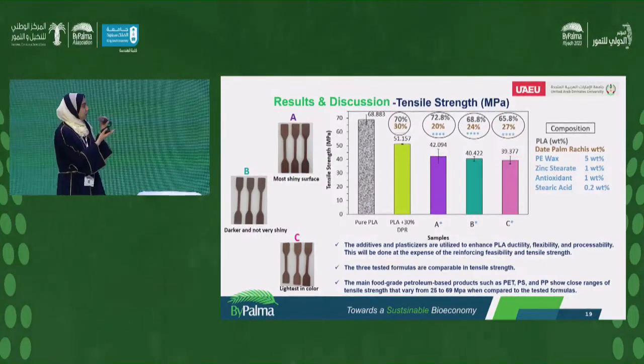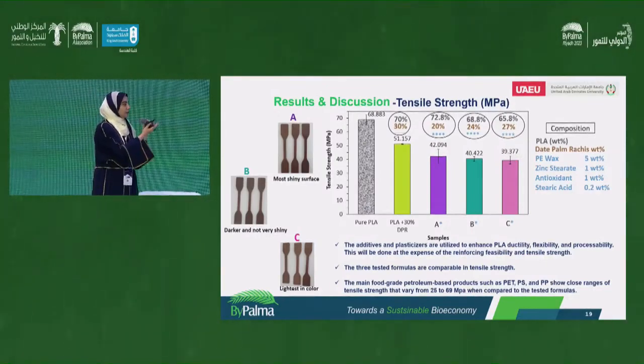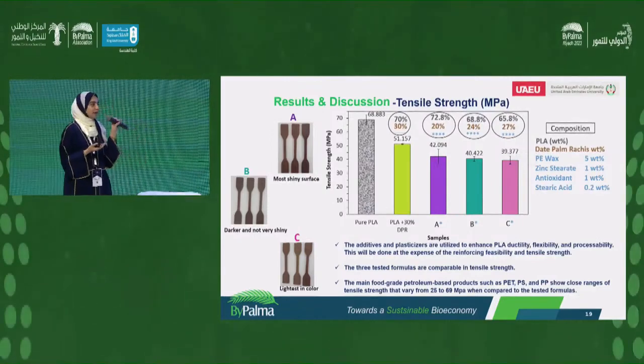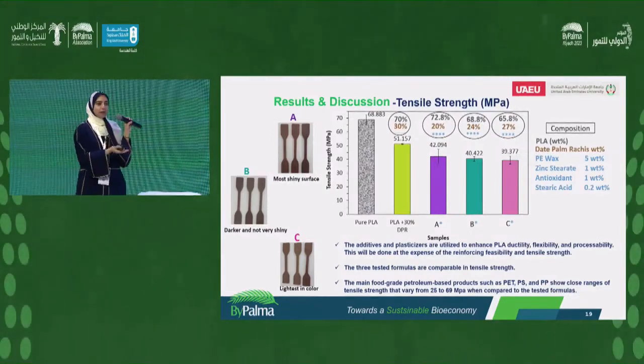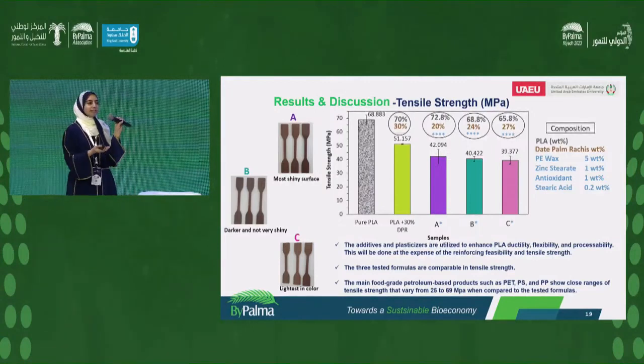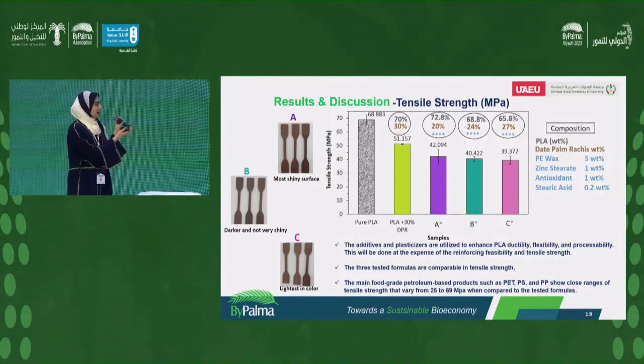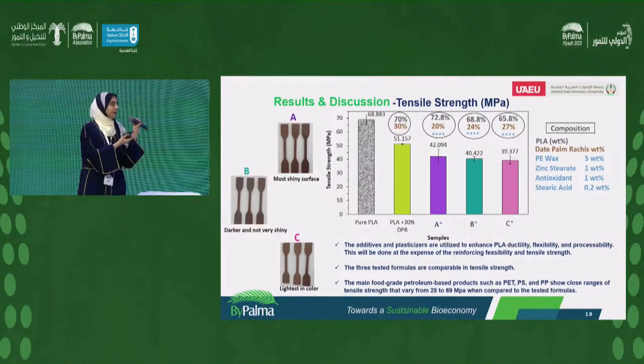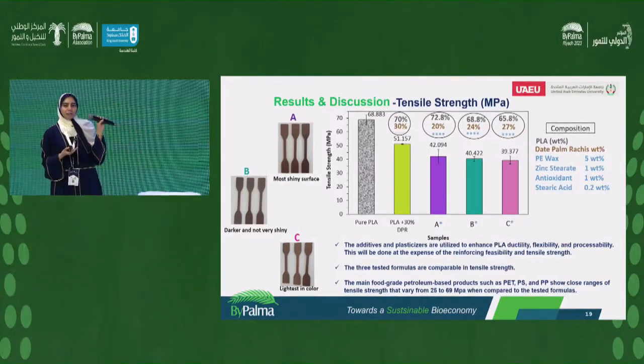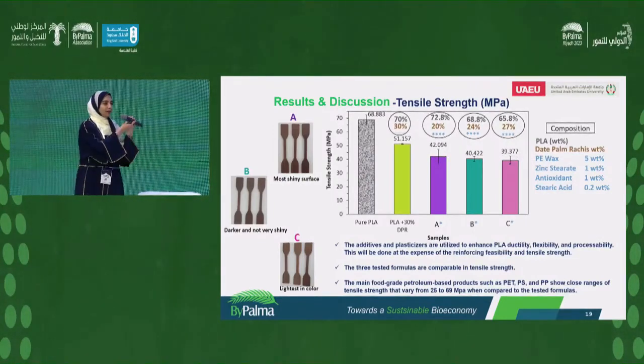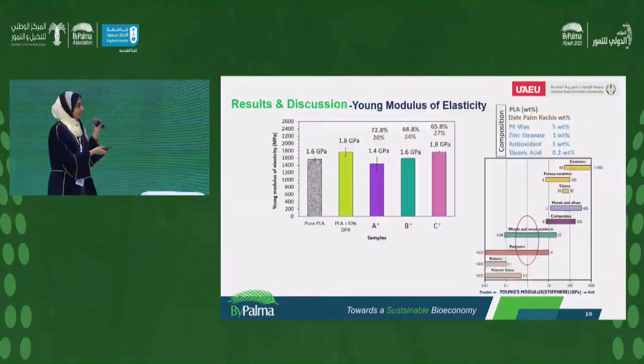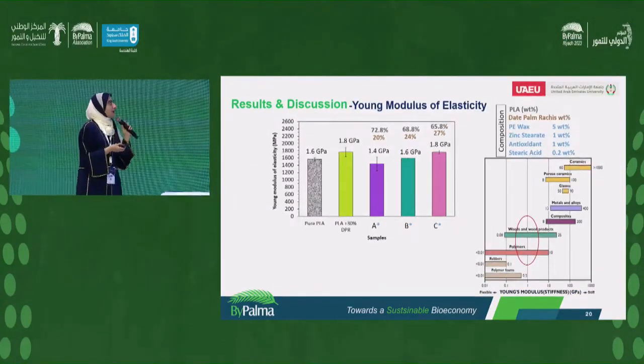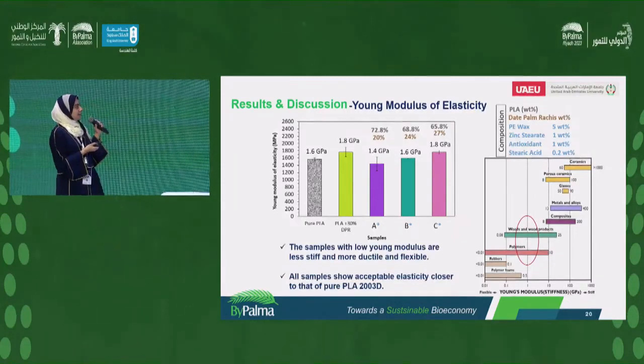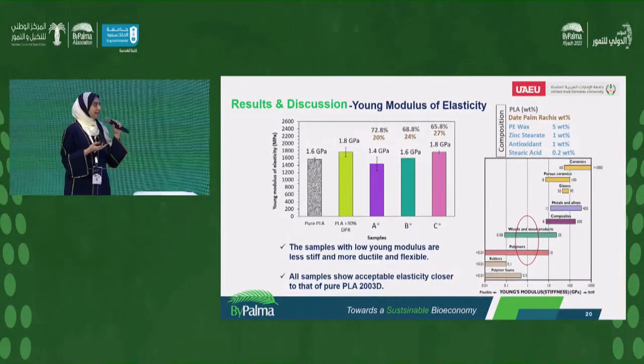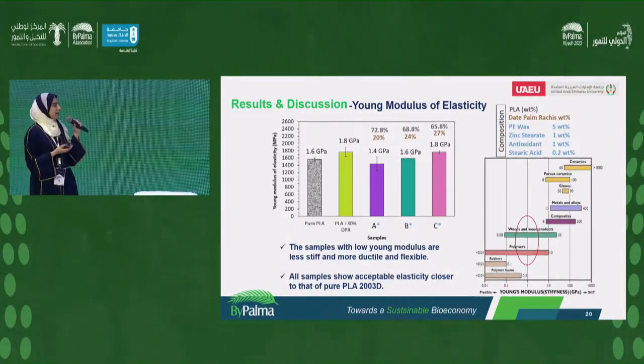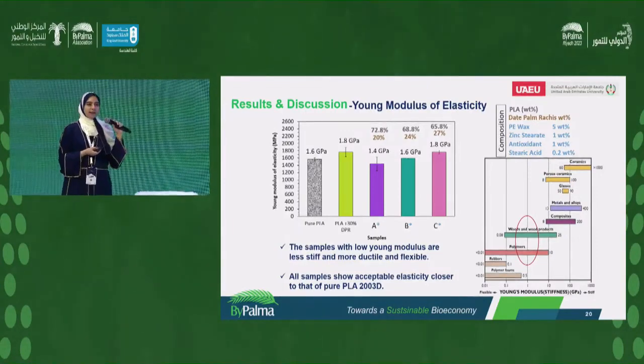And we can see that the food grade petroleum-based plastics such as polyethylene, polystyrene, polypropylene, the ones we use in our water bottles and our plastics, have a tensile strength varying from 25 to 69 megapascal, which is acceptable, and we lie in that range. Moving to the Young modulus of elasticity, samples with low Young modulus are less stiff and more ductile and flexible, and all samples show acceptable elasticity.